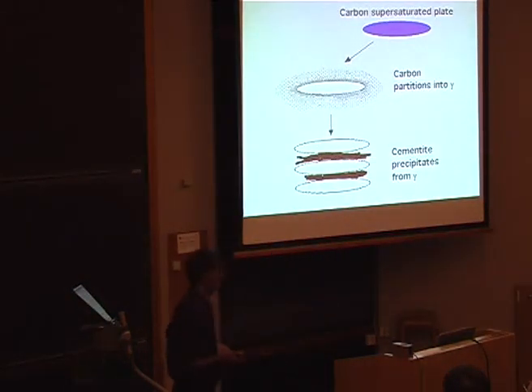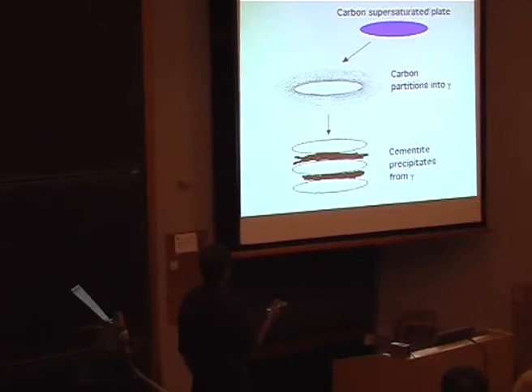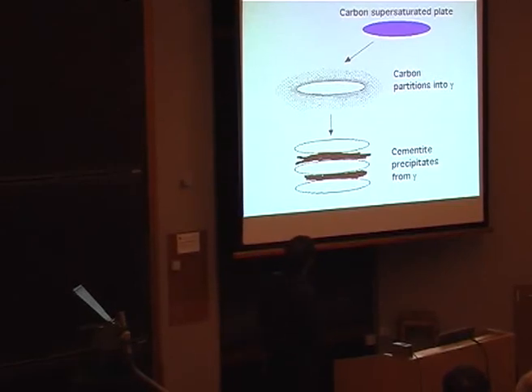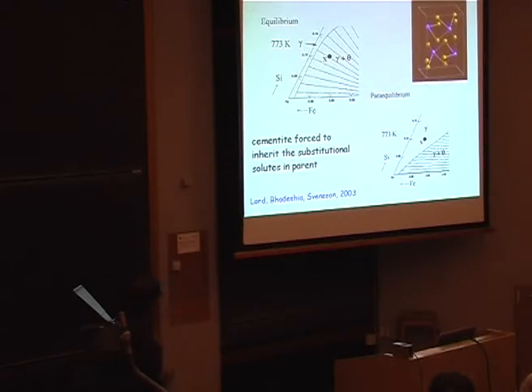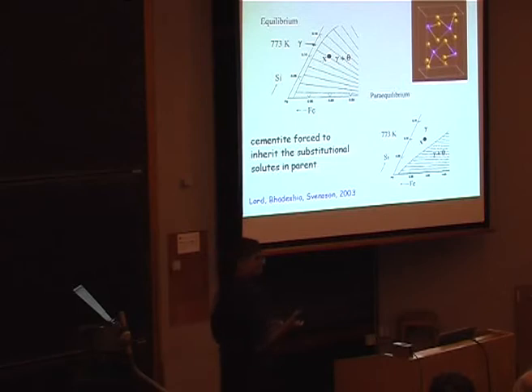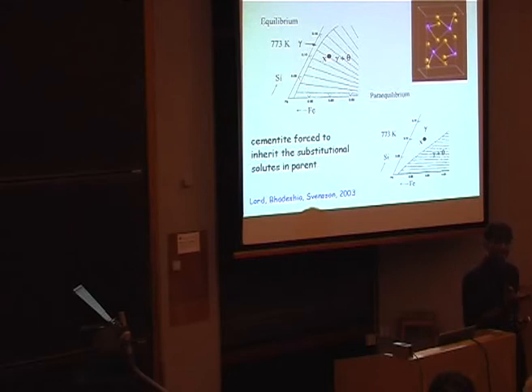The actual mechanism is very simple: you create these completely supersaturated plates of bainite. Without any diffusion, the carbon then partitions into the parent phase and then precipitates as cementite. And this stage can be completely eliminated by alloying because we don't want brittle cementite particles in very strong materials. So if I add silicon to cementite, it raises the free energy of cementite by a very large amount. And another way of saying that is that cementite hates silicon. Because if you put silicon in your steel, you will prevent or retard the precipitation of cementite.